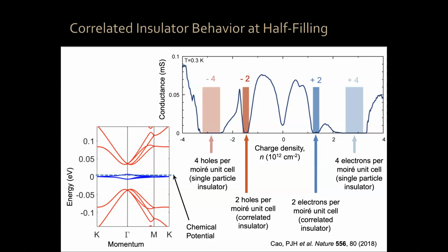Can I ask a question about the horizontal scale? Obviously, if we're dealing with insulators, we're going to have discontinuous bits in the mapping between charge density and chemical potential. Is this really charge density measured in some independent way, or is it chemical potential converted into charge density via some assumption? This is gate-induced charge density. It means I apply a voltage to my gate electrode. I have a parallel plate capacitor, so I know what charge density I'm inducing in one plate of the capacitor. We have independent Hall measurements of what the itinerant carrier density in the twisted bilayer graphene is. That thing is not this continuous axis because there are all kinds of phase transitions happening, because some charges in the twisted bilayer graphene become localized, etc. Okay. So effectively, this is chemical potential as applied to the graphene bilayer, but you're writing it in terms of charge density on the plate.